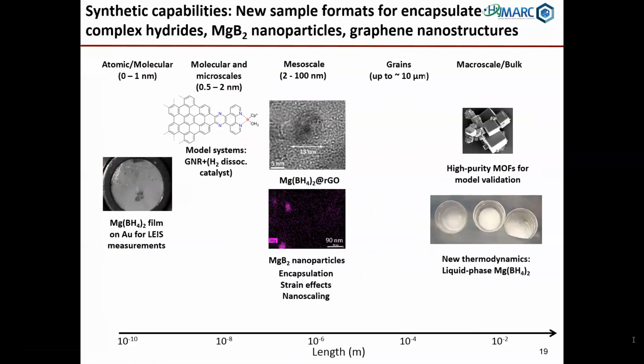On the other end of the spectrum, though, we've developed very well-controlled carbon materials, such as these graphene nanoribbons that are shown here. And these allow us to probe both the interaction of hydrogen with the surface in a way that is far more controlled than would be in a porous carbon, but also we can functionalize the edges of these with catalytic elements and look at the reaction of hydrogen in this very controlled environment, free of a lot of complicating issues that are endemic to disordered materials, various kinds of absorbents, not just carbon.